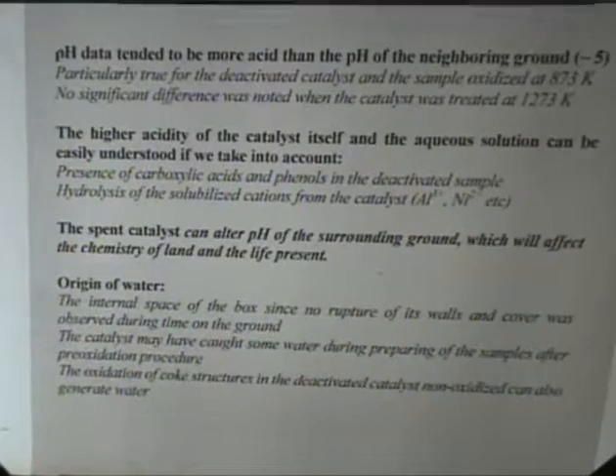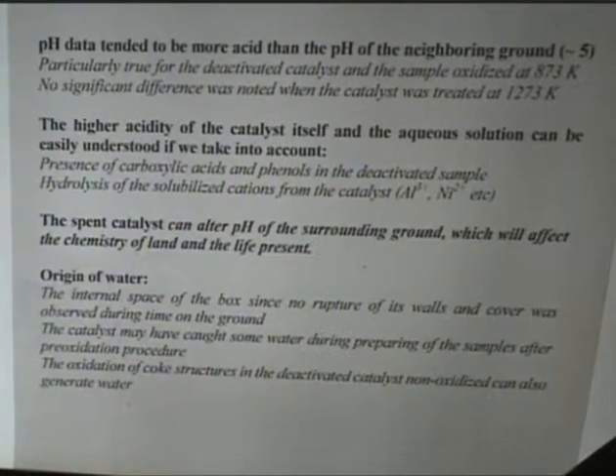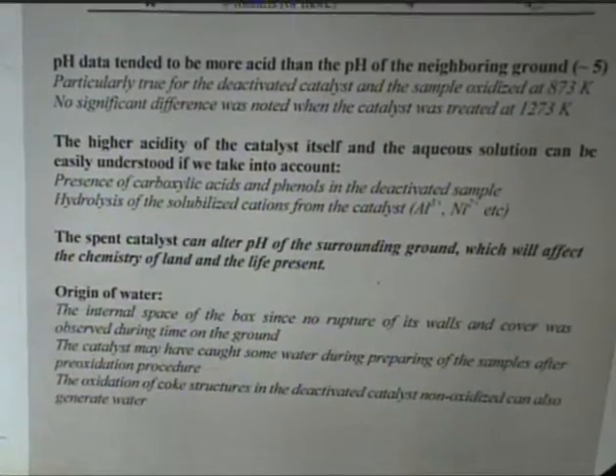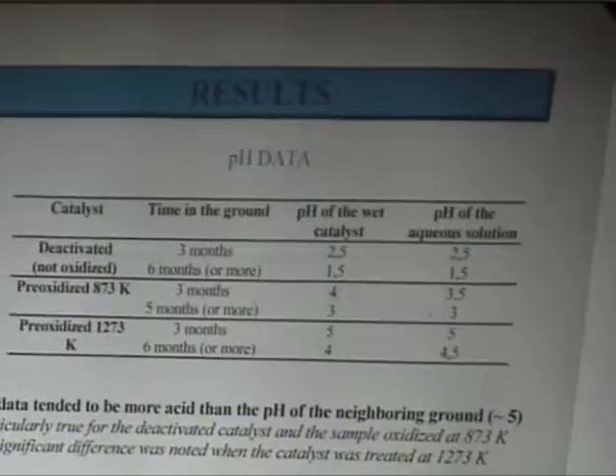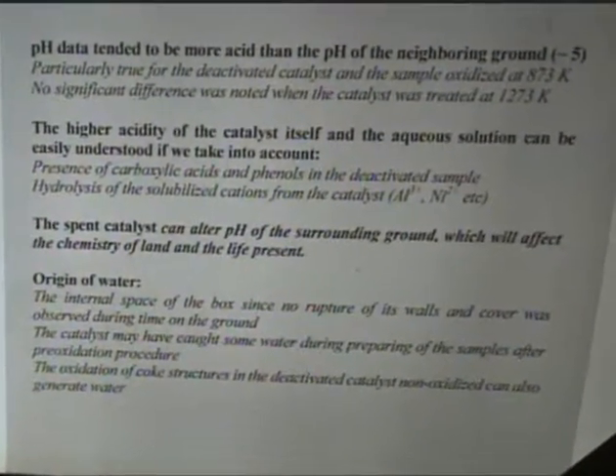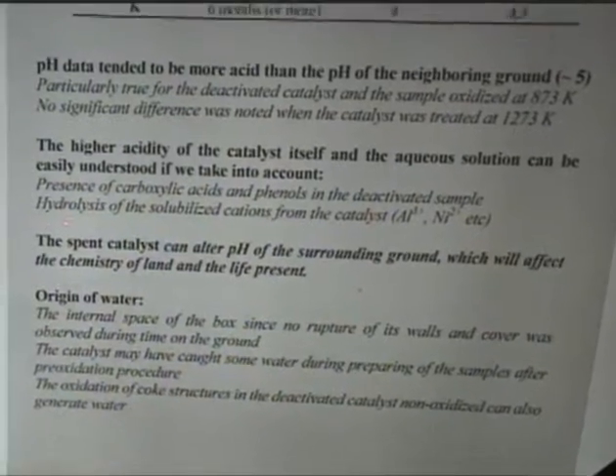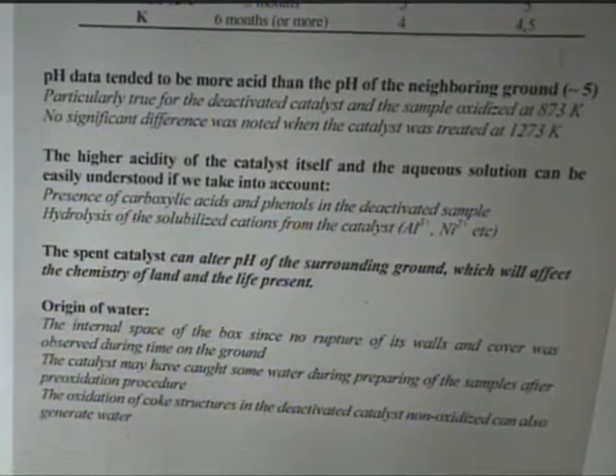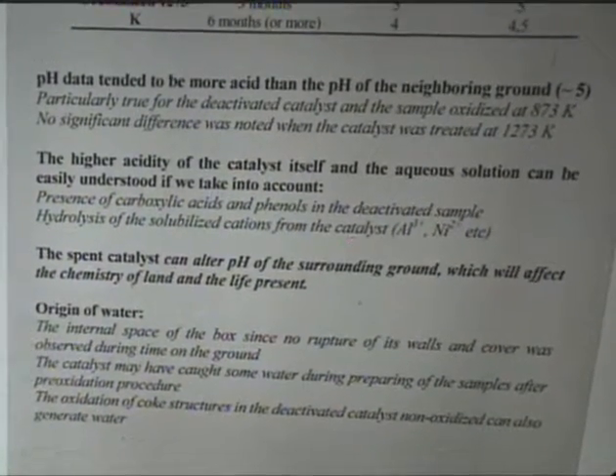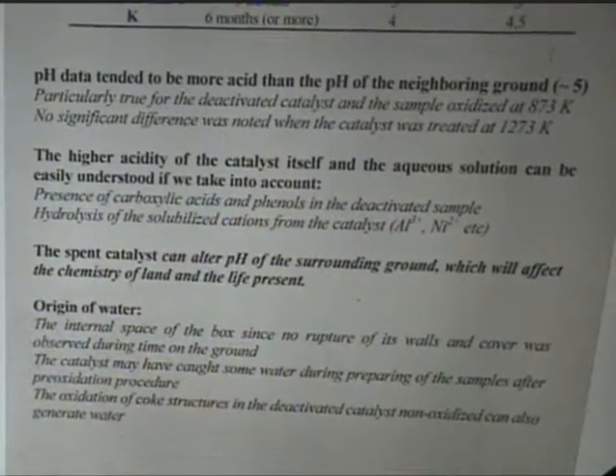Why are the pH of both the wet catalyst and the aqueous solution acidic? Simply because in the case of the deactivated sample, which presents coke, there are carboxylic acids and also phenols among the coke. And as a general explanation, there are hydrolysis products of the solubilized cations from the catalyst, aluminum, nickel, and others.